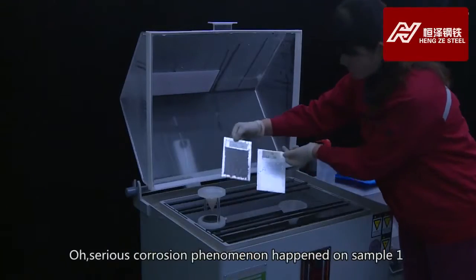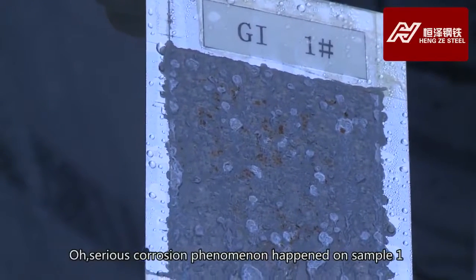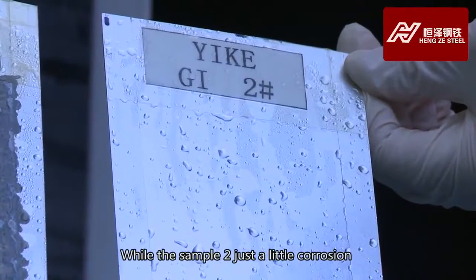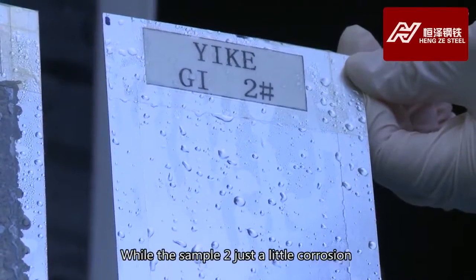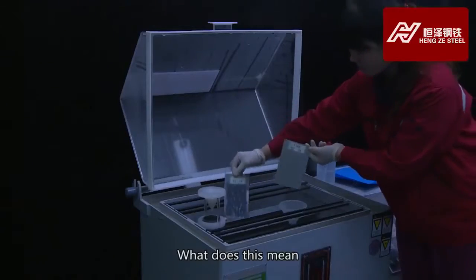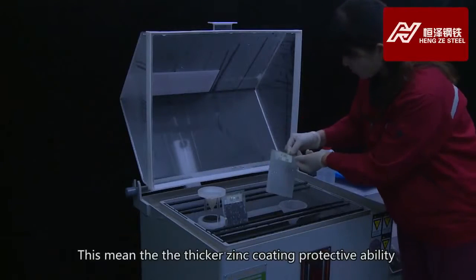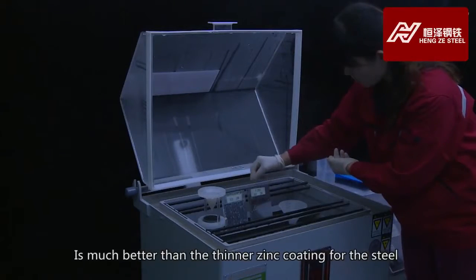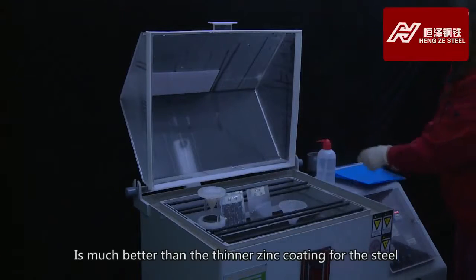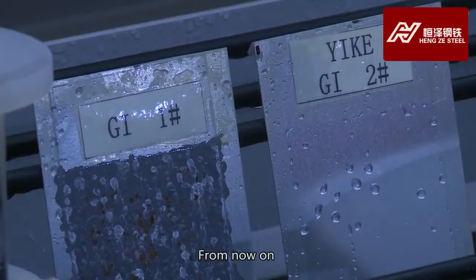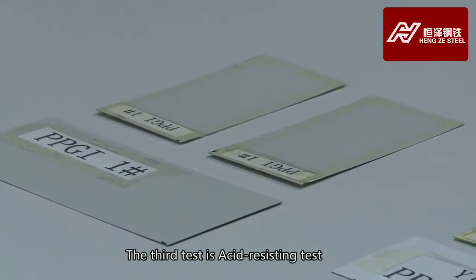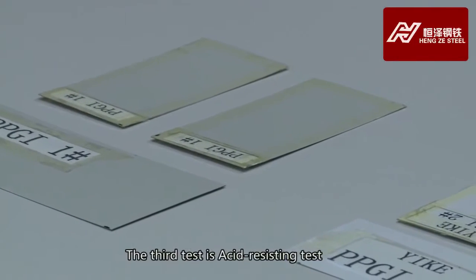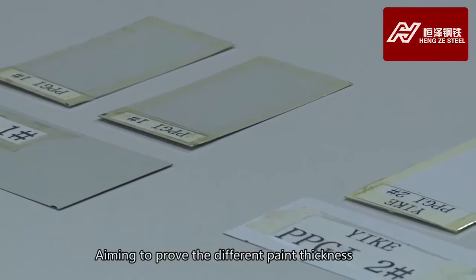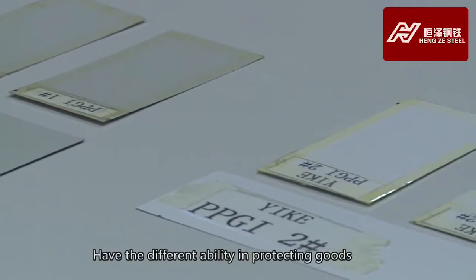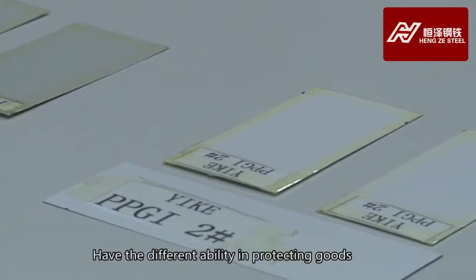Serious corrosion happened on sample 1, while sample 2 has just a little punctiform white rust. What does this mean? This means the thicker zinc coating's protective ability for the steel is much better than the thinner zinc coating. Next, the third test is the acid resisting test, aiming to prove that different paint thicknesses have different abilities in protecting goods.